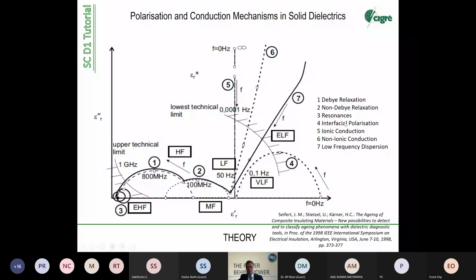So we start with the simple ones. So you know the Debye relaxation, which takes place in the high frequency range. Here's a kind of non-Debye. It's a mixture of many mechanisms taking part in the multi-100 megahertz area. As I mentioned before, resonances are also in the optical range. They are not important for us. So we have to look at 4, 5, 6, 7. 4 is interfacial polarization taking place in the low frequency range. This is the Maxwell-Wagner effect. So this half circle or semicircle in the low frequency range is the Maxwell-Wagner effect.